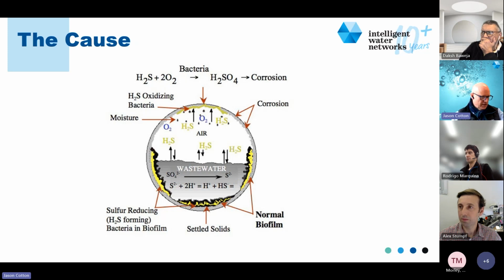And because the water line is not the only part way up the sewer, you do get oxygen. And so that hydrogen sulfide gets absorbed into the concrete. These oxidizing bacteria then have a field day with the hydrogen sulfide, and it forms sulfuric acid. And it's that sulfuric acid that eats away at the sewer. And so that is a wicked problem.